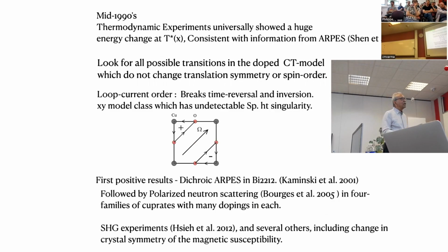So the thing to do, and especially in the mid-1990s, when thermodynamic experiments showed that there's a big change at T star, which I showed you very early on, was to look for all possible transitions in the doped charge transfer model, which do not change translation symmetry or spin order. Again, based on experimental information that along T star, there was no evidence for any change of translational symmetry, and I talked to various people, including Philip, and by that time, neutron scattering had shown that the antiferromagnetic phase goes away well below, and the antiferromagnetic correlation length systematically decreases as you go towards the region where quantum criticality is important for me. So that could not be a quantum critical phase.